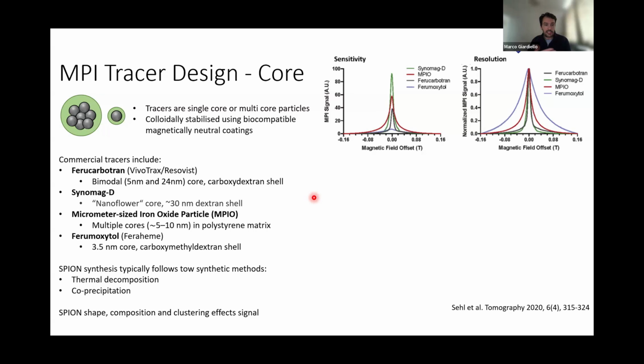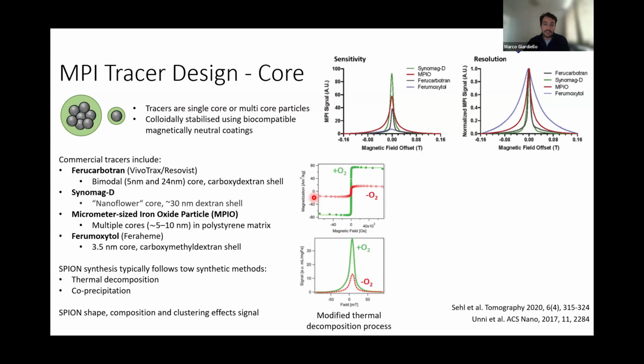Co-precipitation, on the other hand, is much quicker to do. It's basically stirring, not at room temperature, at about 60 degrees, and you get very nice particles, but they're not so crystalline, and by comparison they're not really that great, but they're always just done in water with biologically relevant stabilizers. And here is a couple of examples that I thought I'd put up.